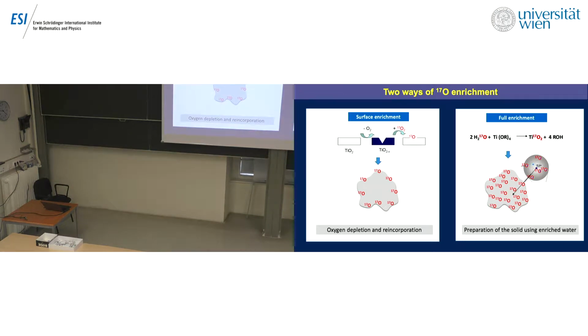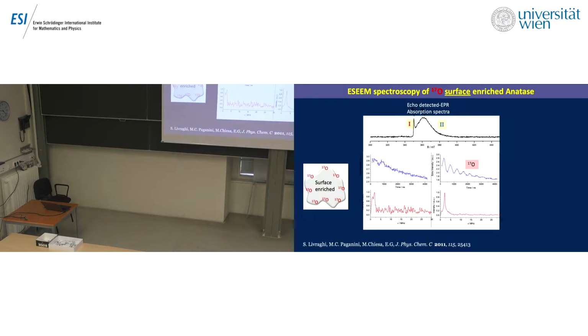Okay, oxygen 17, in this case, we used two different approaches. The first one is to enrich the surface, like in the case of magnesium oxide that I showed at the beginning, to enrich the surface with oxygen 17, and this is simple. You anneal, you create vacancies mainly at the surface, and you restore the oxygen using gaseous oxygen 17. So this is quite affordable. The second method to enrich all the system is much more expensive, I have to say, because water containing oxygen 17 is highly expensive, okay? But if you prepare with some hydrolysis method, that are classical methods to prepare anatase or rutile, you can obtain a sample enriched in all the bulk by oxygen 17. And this allows us to explain what we are observing.